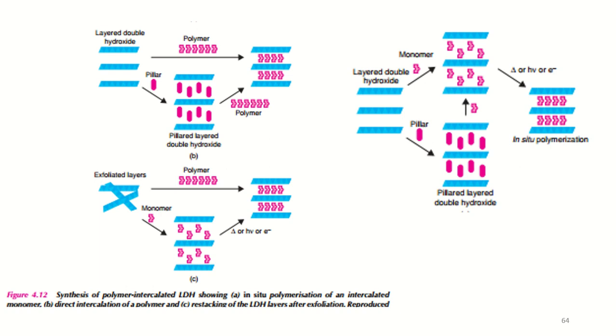In some cases, it is not possible to introduce large anions in a single step, but a two-stage reaction introducing anions of increasing size gradually pushes apart the layers of the host structure.